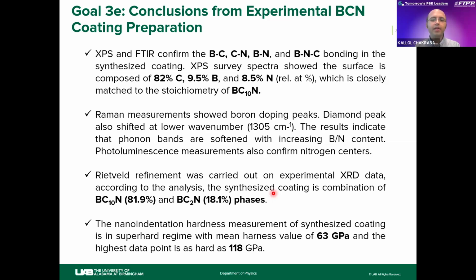The Raman measurement showed boron doping peaks. The diamond peak also shifted towards lower wave number, and the result indicates the phonon bands are softened with increasing boron and nitrogen content. Photoluminescence also confirmed the nitrogen center in our synthesized coating.